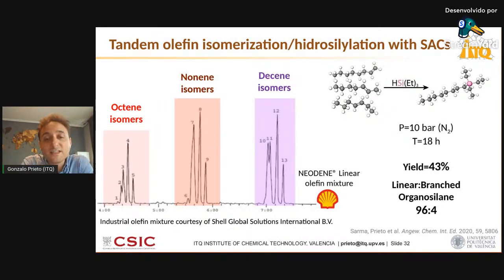And our tandem system could handle that. By a combination of double bond migration plus very regioselective hydrosilylation, it converts them selectively to the terminal organosilanes. As I show here, with a 96% selectivity to the terminal organosilane compared to only 4% to the branched one.